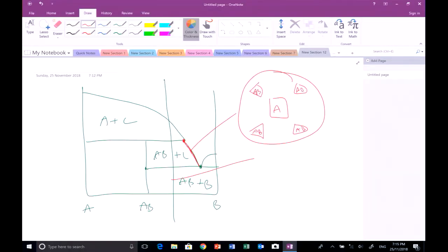Okay? A doesn't want to be there. I've got to get rid of it. If it's resorbing, it's going to redissolve in the liquid, won't it? It's in a liquid, and a liquid's a fast diffusion medium. So A is going to dissolve. And what's going to happen to A is the high surface area corners are going to dissolve off, and it's just going to slowly resorb, leaving you with a more rounded particle. And that's okay.